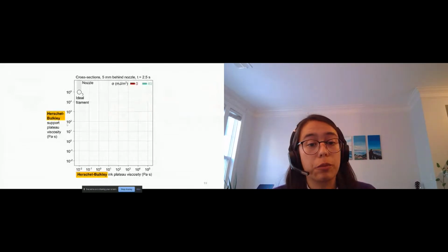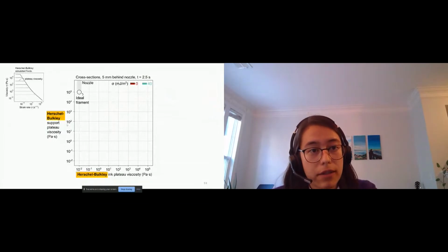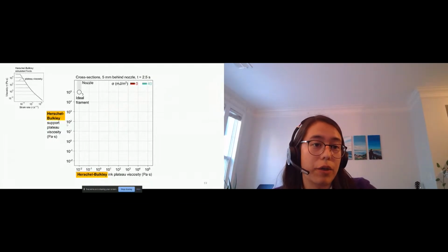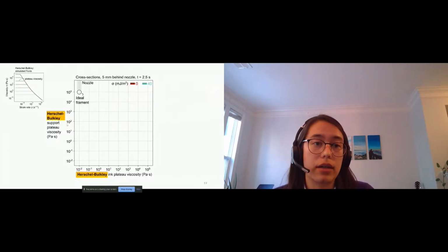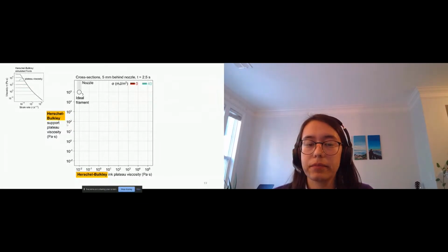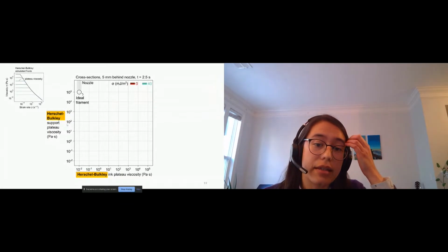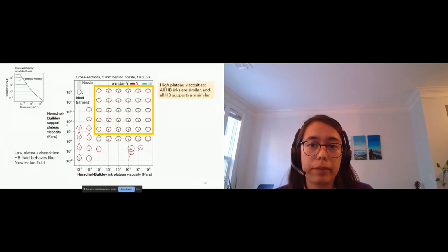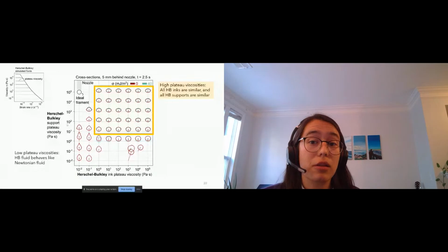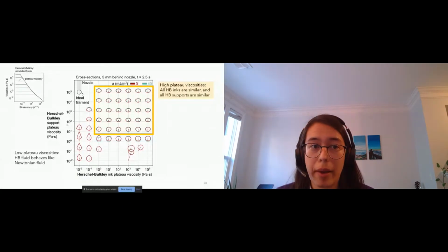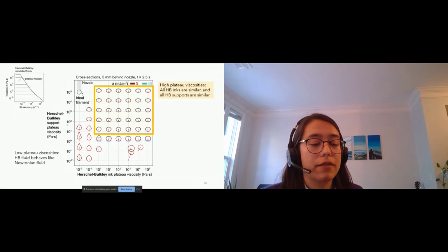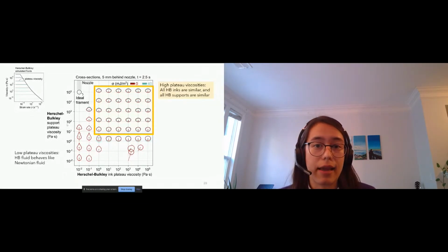Now let's look at Herschel-Bulkley fluids. So here we're going to have a constant plateau viscosity up until yield stress, at which point the viscosity will drop off towards shear thinning behavior. So here what you can see is if you go to a high plateau viscosity for both the ink and the support, beyond a certain point, all of the cross sections are the same. So all of these Herschel-Bulkley inks behave similarly and all the Herschel-Bulkley supports behave similarly. And remember, the way that we set these viscosity curves, the viscosity above yield is the same for all of these.